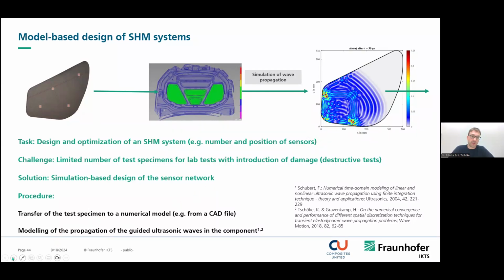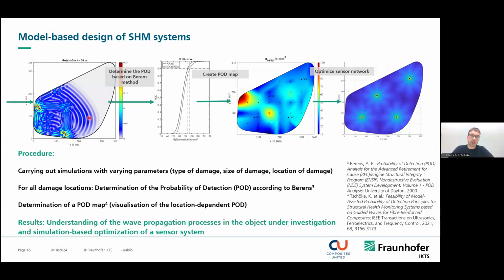And then we can model different damage positions, different sensor positions, analyzing them by using statistical methods. For example, the known Berens method, which is known from the aerospace. And by using this statistical method, we can get information about the probability of detection, which means the probability to detect a damage of a specific size on a defined location. And by knowing this, we can optimize our sensor network. We can optimize the sensor positions and the number of sensors to get the best probability of detection for defined sizes of damage. So we have to know the critical size of the damage, and then we can optimize our